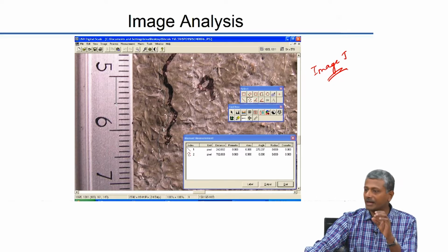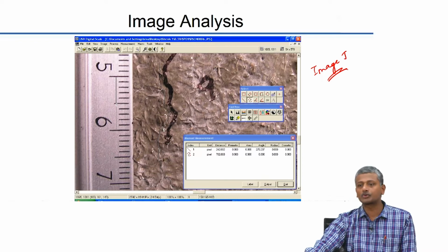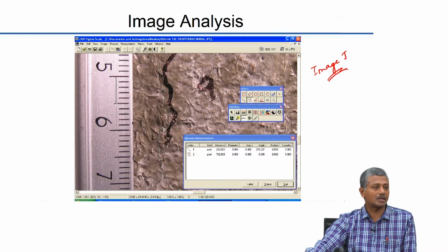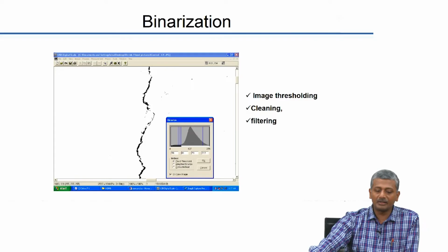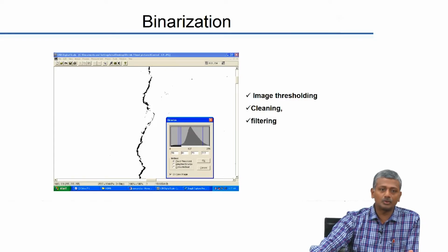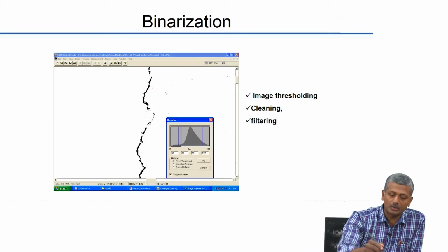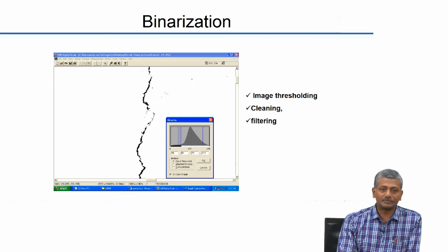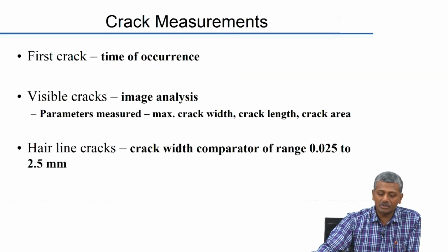You might need a crack width comparator or the crack width microscope that you might have used in your structural engineering laboratory experiments. So, after we do the image collection, we do the binarization, which gets us the actual image of the crack itself. All the other parts are turned into white and only the crack part is black, okay. And then based on that, we can determine several features related to cracks.